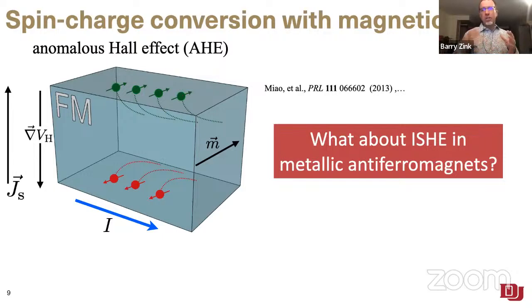So here what we have in a metallic ferromagnet is a spin polarized sea of electrons. So already we don't have the average numbers of spin up and spin down electrons canceling each other out, you know, on average, no spin polarization. We've tipped this toward having some polarization of the spins, which means that now if you drive a current through this thing, the same thing happens. You still can have spin orbit coupling. You still have this sort of transverse flow of the up and down electrons, but now that we have this imbalance between the ones going up and going left, that means we still get a spin current, but we also get a charge current because we had interrupted this balance between the two. And that charge current is very important, has been known for something more than a century. That's the anomalous Hall effect.